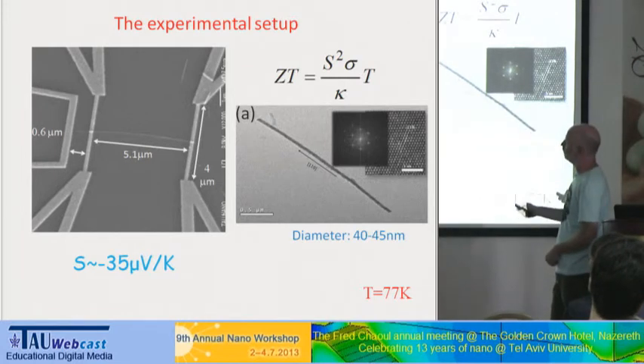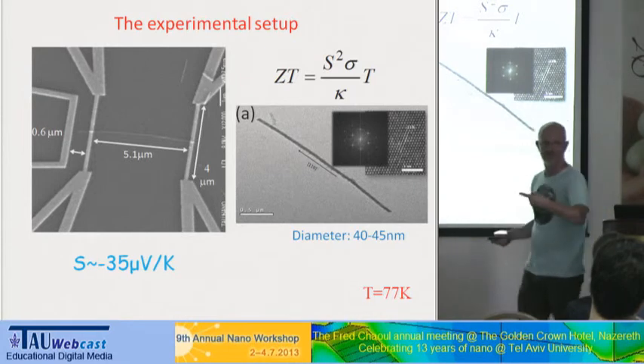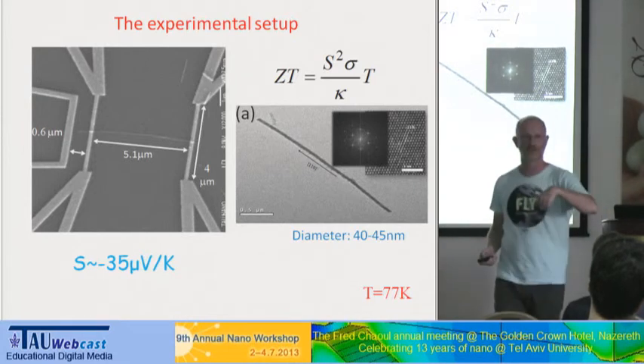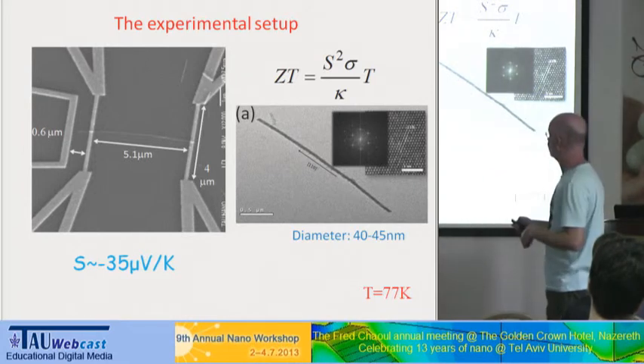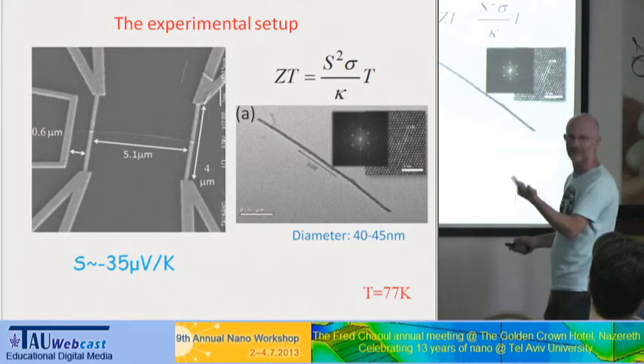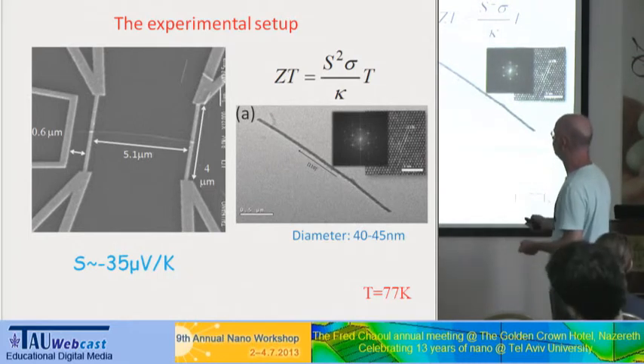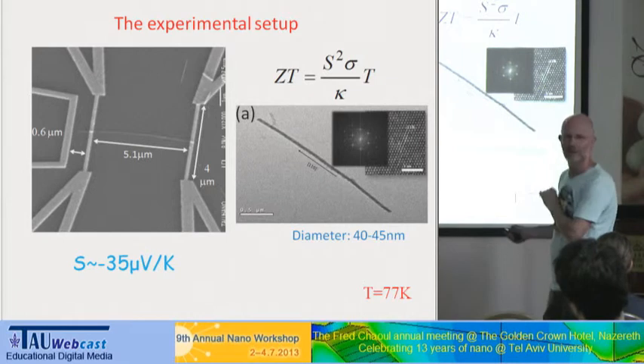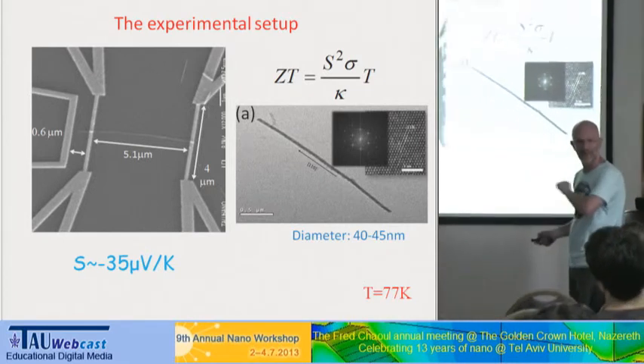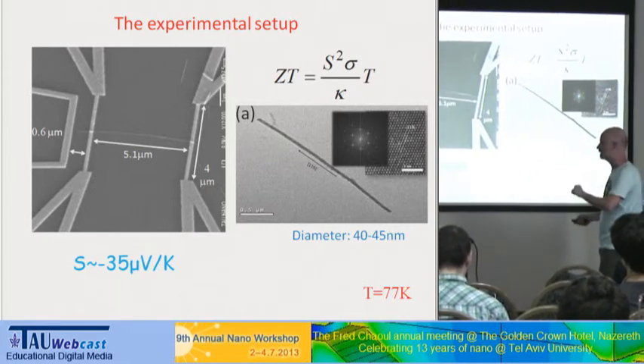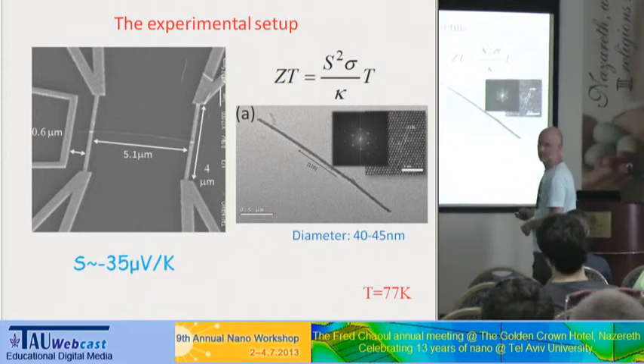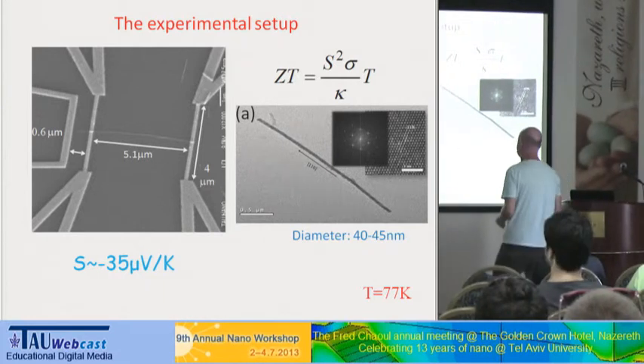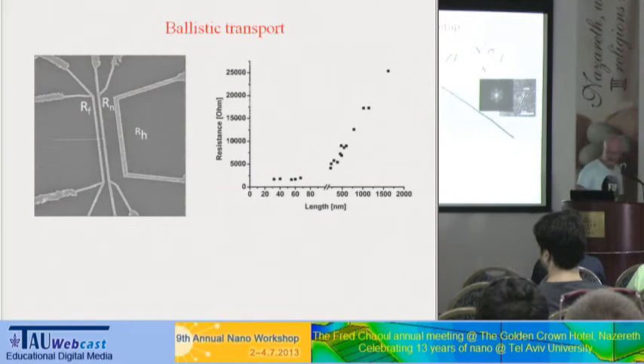We simply make 4 probe measurements and measure small changes in the resistance of this wire here, which is made of gold. And by the change of the resistance, we know what is the temperature that you have on both sides. So we know delta T. So we have delta V, we have delta T, we know the Seebeck. And the Seebeck of the wires that we are making is quite high. It's minus. It should be minus because the electrons are the carriers inside bismuth. But this is really low. We wish to see something which is much better than that.